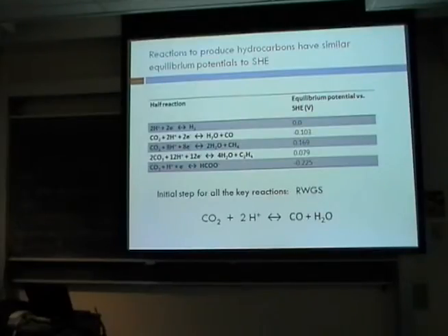And I'm not showing it here, but in the direct electrochemical reaction where you're adding lots of protons and electrons, you can actually get formation of 3 carbon and higher chains directly out of the photoelectrochemical process. Okay, so far the yields of those have been low, and so that's a big direction of research, is trying to find a catalyst that directly can make hydrocarbons from CO2, and really the longer the better. It would be great to have a directly usable fuel stream coming straight out of the electrochemical cell.